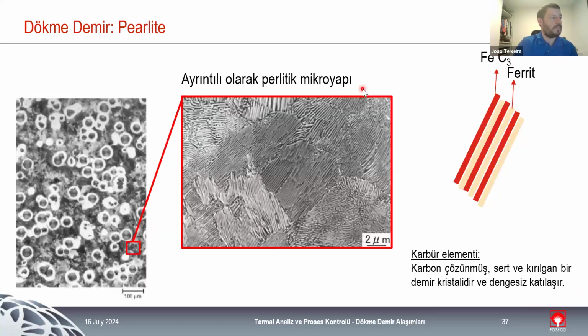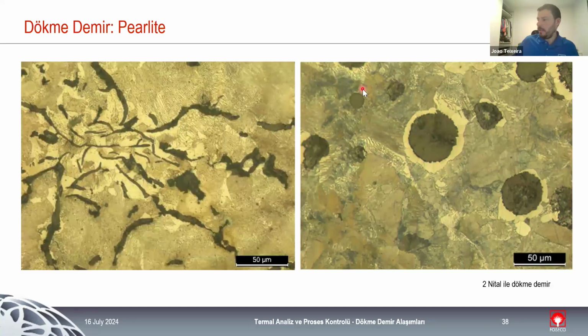And you can see here that they are oriented, all the pearlitic structure that we have, normally with the addition of copper and tin in nodular. They are oriented, and we know this orientation, and we know that if we add a specific amount of copper and a specific amount of tin, we are going to have a specific amount of pearlite. So we can play with these windows to improve the mechanical properties without decreasing a lot the machinability of the cast.